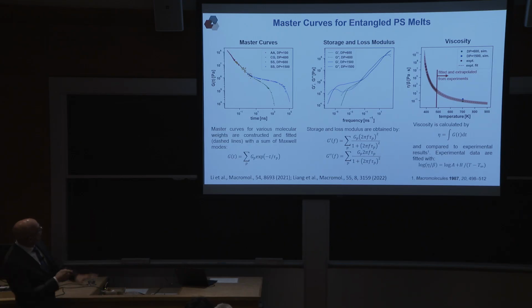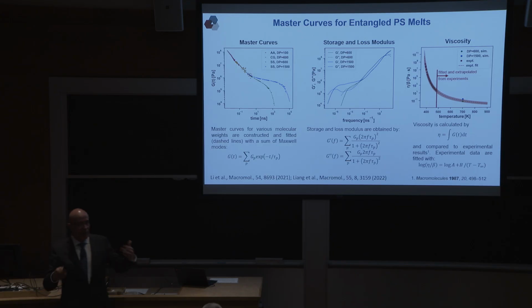So once you put all your data together, you can create these master curves. So here you see the stress as a function of time for polystyrene, different degrees of polymerization. At the shortest timescales, very fast motions, the atomistic representation is shown in red. Then you go to the coarse grain, shown in yellow. Then you go to the slip spring, shown in blue or in green. And they all overlap with each other, they match with each other, and you reconstructed the entire relaxation curve for the system over, in this case, 7 decades of time. That's the problem that we were trying to solve.